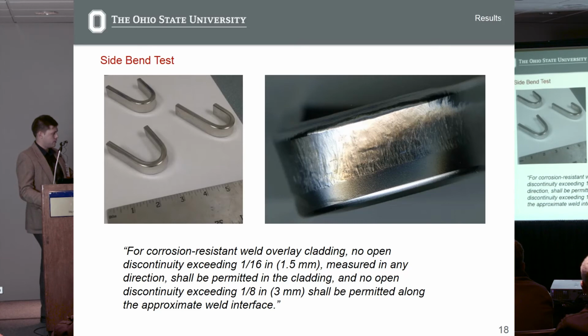So I cut and pasted a little quote from ASME Section 9 for boiler and pressure vessel welding. For corrosion-resistant overlay cladding, no discontinuity exceeding 1.5 millimeters in any direction shall be permitted, or any open discontinuity exceeding 3 millimeters shall be permitted. After side bend testing at 180 degrees for a total of 20% elongation at the surface, there were no open discontinuities whatsoever to be detected. Again, positive result. No defects detected.